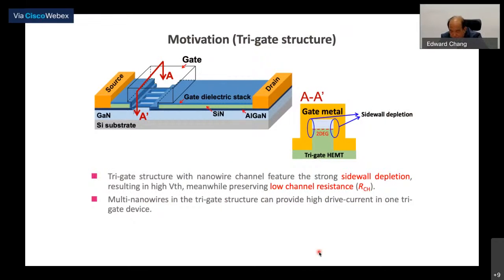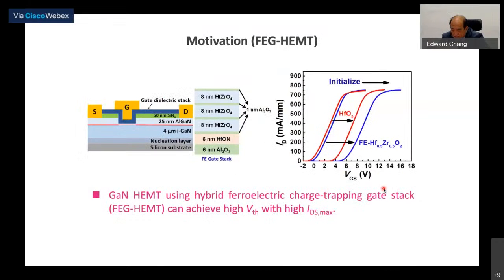The channel resistance needs to be decreased too. So in this way we use thin structures, a tri-gate structure with nanowires about 100 nanometer, because 100 nanometer enables you to deplete the channel, so it becomes E-mode. Also, because of this you have the 2DEG and an inversion layer on the gate sidewall, and then you can make a very low channel resistance. So we have multiple nanowires to create enough current. And this is the structure that you can use.